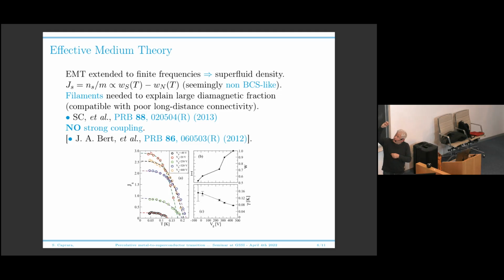And the coefficient of this reactive response is related to the superfluid density of your superconducting cluster. Now, it is very easy to find that in effective medium theory, this superfluid density is the difference between the fraction of superconducting bonds and the fraction of metallic bonds as a function of temperature. So if you have more metallic than superconducting, this quantity is negative, which means that you have no superfluid response. If this is larger than this, which means that you are above 1/2 for your superconducting fraction in a homogeneous system, then you will have a superfluid response in your system.